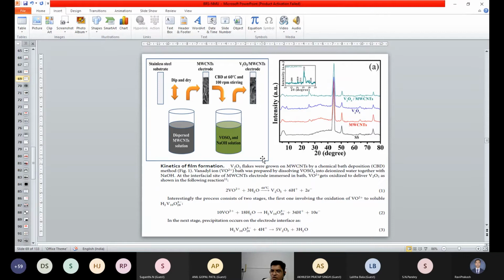From NaOH you can get a certain oxide part, right? And then vanadium reacts with the oxide part, and then you can use this at a certain temperature, and we have used 60 degrees Celsius. Carbon nanotube coated on the stainless steel substrate, we have dipped inside this for a certain time at 60 degrees Celsius, and we have seen that vanadium oxide is coated on the carbon nanotube.